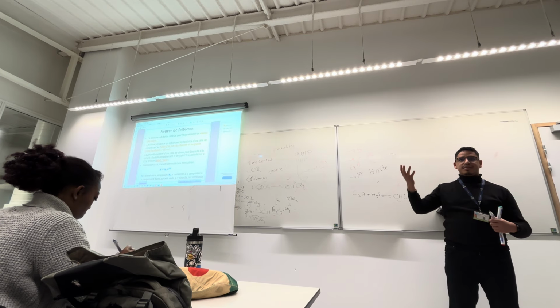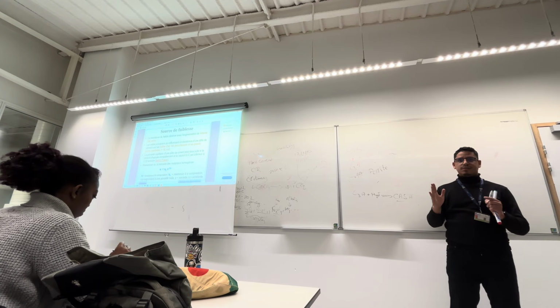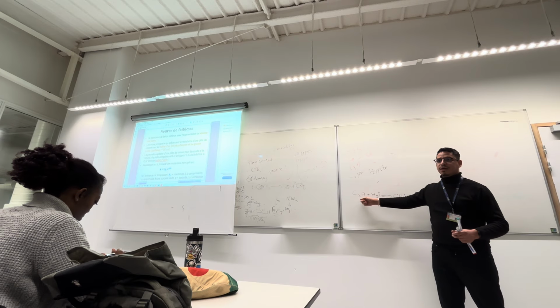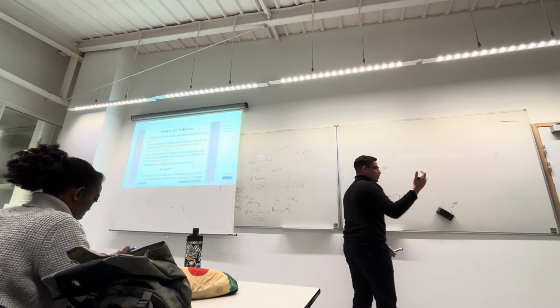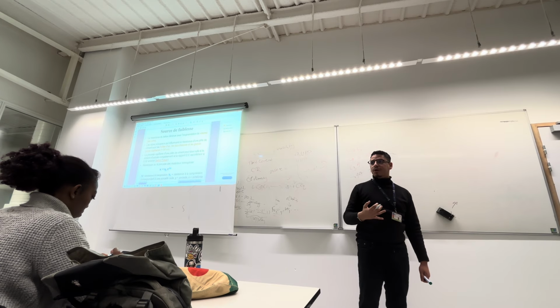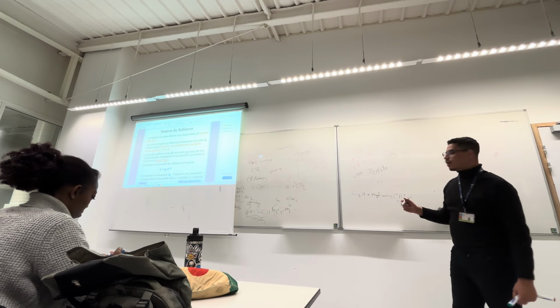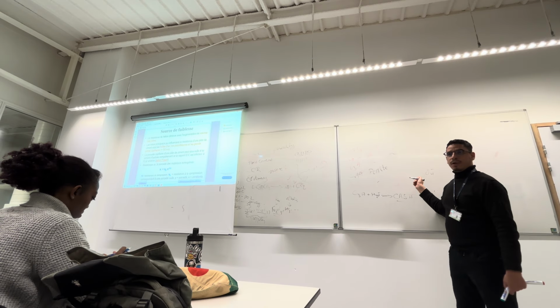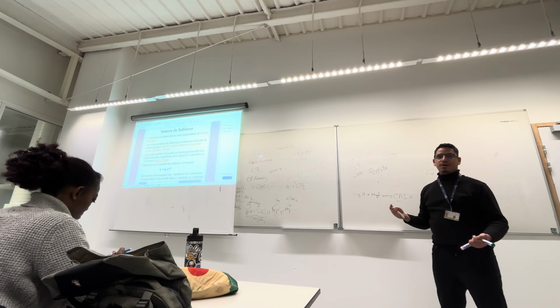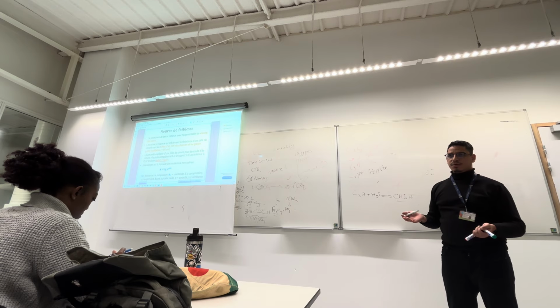So C3A gives us an increased hydration heat. So the first thing, we need to reduce C3A. C3A reacts with the sulfate SO4, when we have sulfate, maybe coming from seawater or used water. So maybe our concrete will be exposed to sulfate attack SO4. And this will react with the C3A and give us what we call secondary ettringite. And this ettringite will crack our concrete.